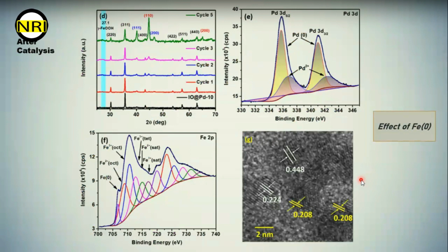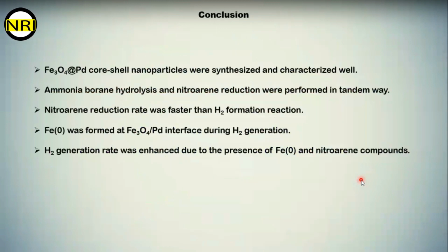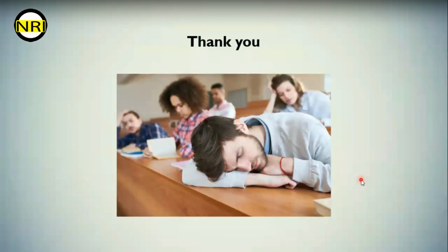So with this, I wanted to complete my talk, and here is the conclusion. I synthesized Pd-Fe3O4 nanoparticles with a solid-state synthesis process and characterized them well. Then ammonia borane hydrolysis and nitro reduction were performed in tandem. From this analysis, we observed that the nitro reduction rate was faster than the hydrogen formation reaction. During this hydrogen generation reaction, iron 0 was formed at the Fe3O4-Pd interface, and this Fe0 and the nitroarene both enhanced the hydrogen generation rate. Thank you very much.